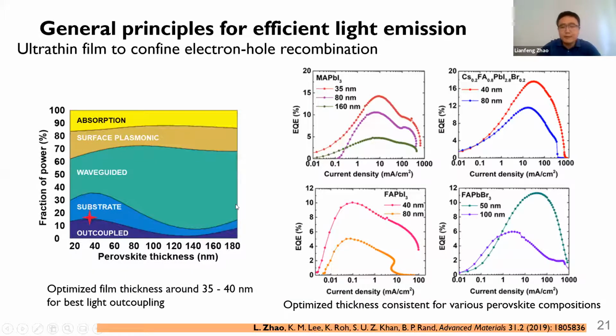For planar device structure, most of the light is trapped because of the total internal reflection in the device structure. By optical simulation, we found that the optimized film thickness is around 35 to 40 nanometers. These simulations are confirmed experimentally with different perovskite compositions. For all these compositions, we get the highest EQE with thin films around 40 nanometers.